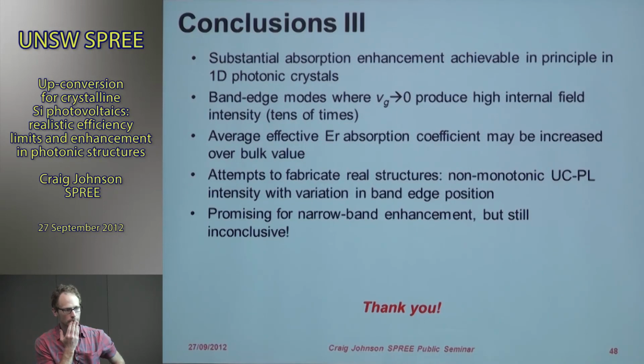How do you get the erbium into them? The erbium then, you do the same process in reverse polarity with the substrate on a cathode and immersed in solution. And you electroplate, and the erbium simply diffuses into the pores in solution form and then deposits itself on the walls. Deposits on the wall? Yeah, not into the silicon. You can get it into the silicon by annealing to some extent. Yeah.